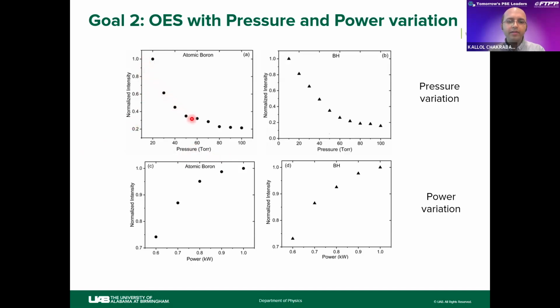The same thing happens for the BH peak intensity - when we increase the pressure, the BH peak intensity also decreases. Now, in the bottom panel, we keep our pressure constant and increase the power. As you can see, when we increase the power, our atomic boron peak intensity increases, and similarly the BH peak intensity also increases.